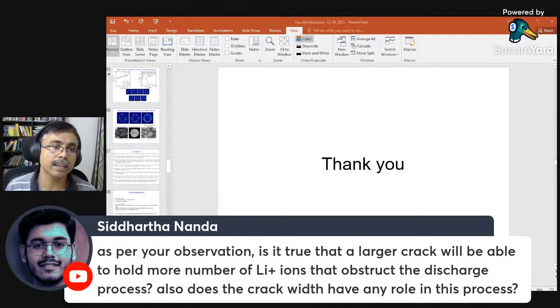If there are multiple cracks, multiple stress concentrations will build up. At the crack tip, there is a tensile field ahead of the crack tip that will try to pull things together towards the cracks. That is a very well-known phenomenon in materials science, for example hydrogen embrittlement in nuclear safety, where hydrogen goes towards the crack tip. Okay, so the question is how the path is disconnected. When I showed that the particle-matrix interface is broken, then the drastic capacity fade happens, which we do not anticipate.